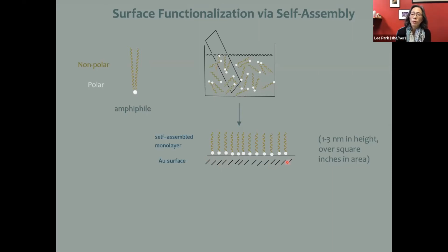The thing that happens is that the polar head groups interact selectively with the gold surface. And what you end up with is a gold surface where you have an extremely well-ordered arrangement of these molecules with the polar head groups bound to the surface and these greasy tail groups sticking up in the air. And the thing that's remarkable about this is you take your gold slide, which might be a few square inches in area, and you dip this in your solution for a very short period of time. And you can organize these molecules based on this property of self-assembly very quickly. And so this would be the equivalent of taking yardsticks and managing to get them all lined up on end over an area of square miles. So it's really actually pretty remarkable.